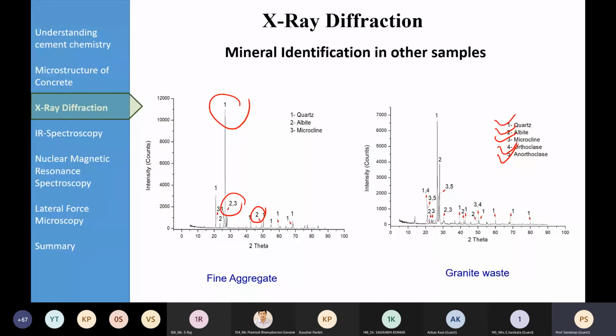So what benefit we are getting from these XRD images is that we very well know in the beginning only that once we replace the fine aggregate by the granite waste, then basically two more types of minerals will be there, orthoclase and anorthoclase, which are not there in the fine aggregate, conventional natural fine aggregate. That means whatever effect we will be observing, that effect will be basically the effect of orthoclase and anorthoclase.